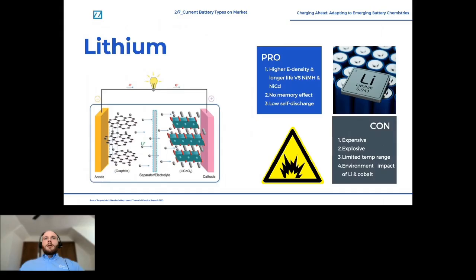Lithium ion batteries last around 2 to 3,000 cycles, while lithium iron phosphate batteries can last even longer, up to 10,000 cycles. And these numbers can vary widely based upon the environment the battery is in, temperatures it's in, that sort of thing, as well as the amount of recharge and discharge. Lithium ion has the positives of being lighter weight, more energy dense, having a longer life and does not require the ventilation compared to these older technologies.